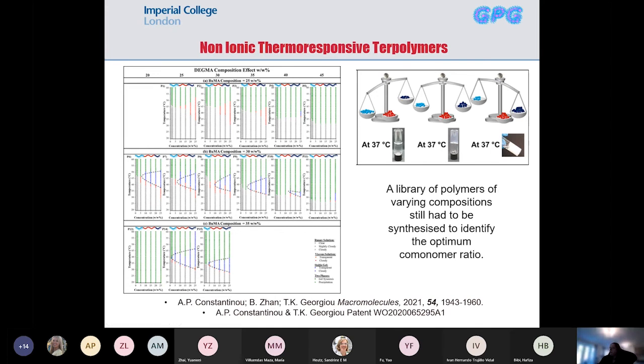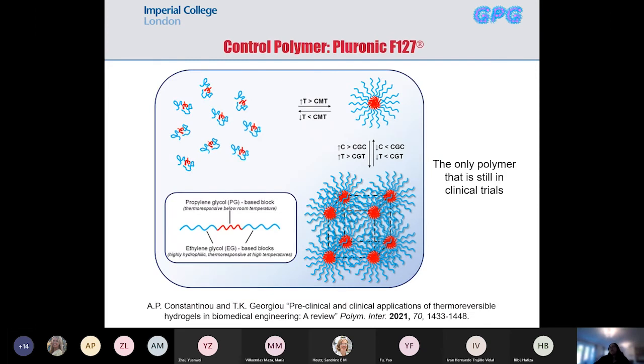So if we compare this with Pluronic F127, that is a polymer that I mentioned earlier that was used for 3D printing. Pluronic F127 is also the only thermogel polymer that is currently in clinical trials. All the formulations that are currently in clinical trials have this known biocompatible Pluronic F127, a commercially available polymer. Pluronics were first patented by BASF, and they are based on polyethylene glycol and polypropylene glycol groups.